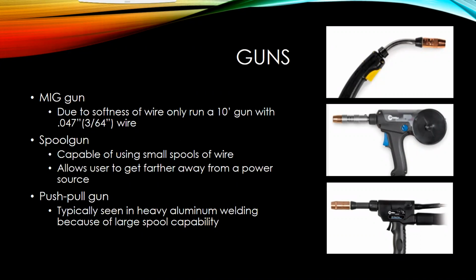Next thing I wanted to touch on was guns and where they have benefit and where to use them. So for welding aluminum, you can use a regular MIG gun, but what you want to make sure is that you use typically a 10-foot gun. Typically, if you're going to run a regular MIG gun, you're only going to be wanting to run 047 or 3/64 wire, that bigger wire diameter for aluminum, because the wire is so soft. If you go any smaller with diameter, you might see some bird nesting. So with that 047, usually it's stiff enough that you can run it through a 10-foot gun, but it's critical that you have the appropriate liner for that, which is Teflon. But this makes a great setup for a shop running that 10-foot gun, because typically you can be right next to your car that you're going to be welding on, and you won't need the additional motor to push that aluminum.